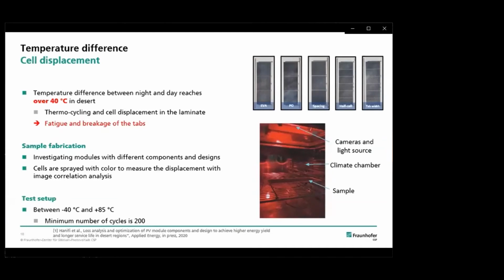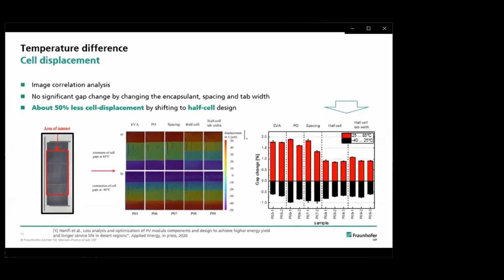Then we used temperature cycling between -40 and +85 degrees. And on this slide, you can see the results of image correlation analysis. Seeing the original image on the left side with the area of interest, and then in the center you can see an image with a color code depicting this displacement. And the most interesting is the graph on the right hand side, indicating the gap change for different temperature ranges.